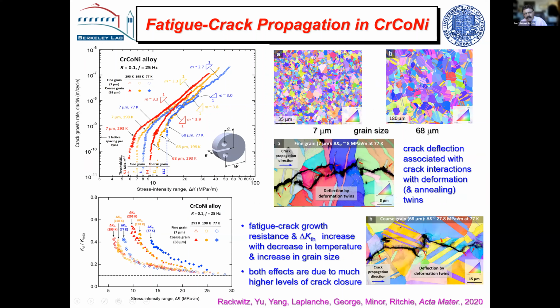This is the coarse grain structure here, fine grain structure here. Again, blue is liquid nitrogen, red is room temperature. But that's really a closure effect. So there's nothing particularly exciting about this. The crack propagation data is comparable or better than most comparable alloys.